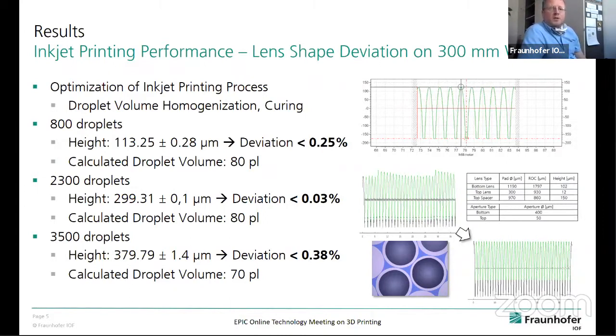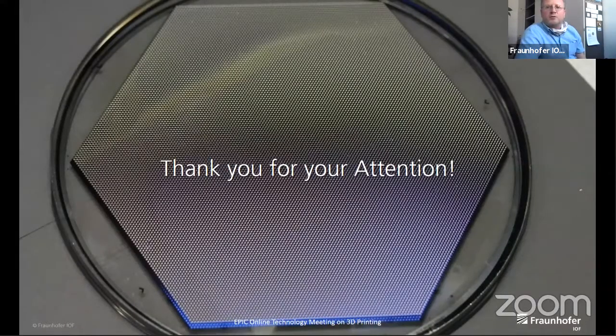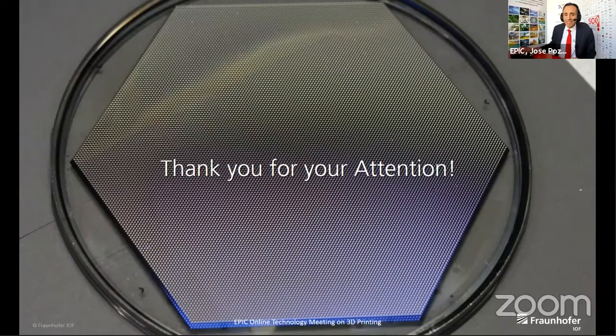Nevertheless, we are still able to get a very precise shape when optimizing the process, with the deviation of the height and also the radius of curvature much less than 1%. And that on an area up to, let's say, 300 millimeter wafers, and we believe that can even be achieved on the meter range. And that actually already brings me to the end of my talk. You see a 300 millimeter wafer here in the end, completely printed with a microlens array, and this is used for an artificial sun illumination application. So thanks for the attention.